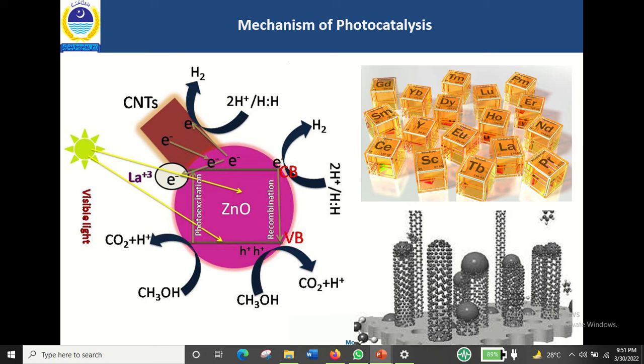At the same time, carbon nanotubes act as an electron sink, meaning the electrons get trapped in the carbon nanotube structure and therefore do not spontaneously return to the valence band without participating in the photocatalytic activities. These trapped electrons effectively contribute to the photocatalytic activity of the zinc oxide.